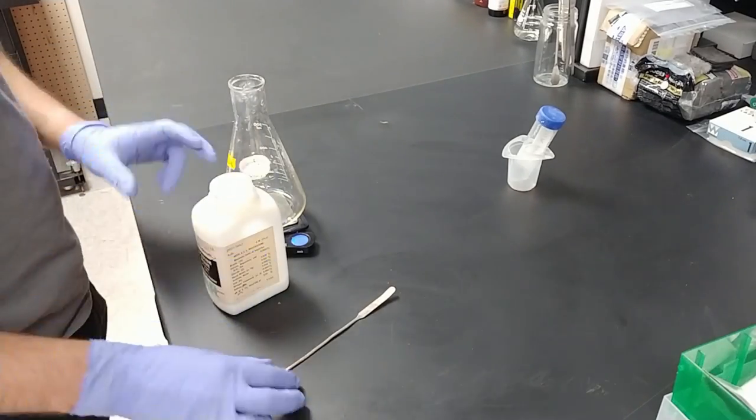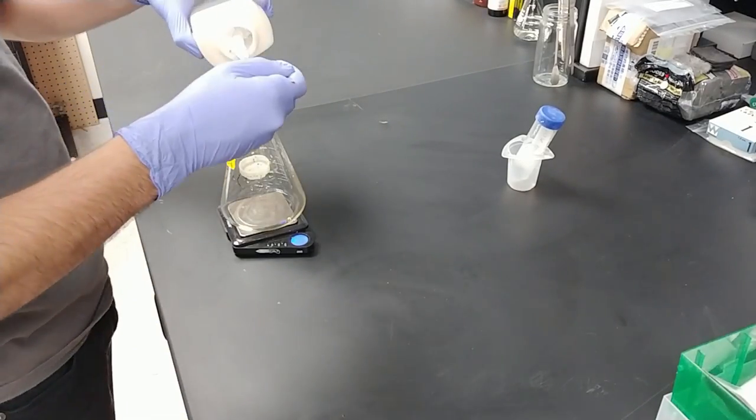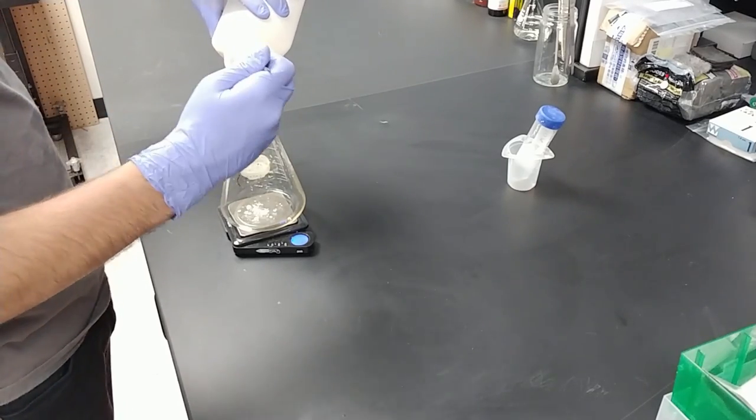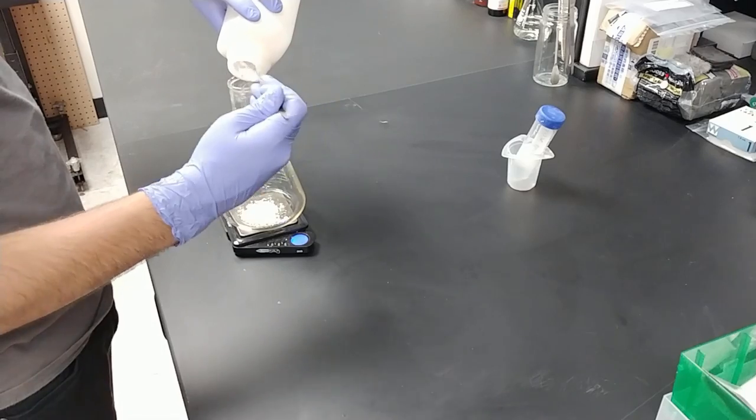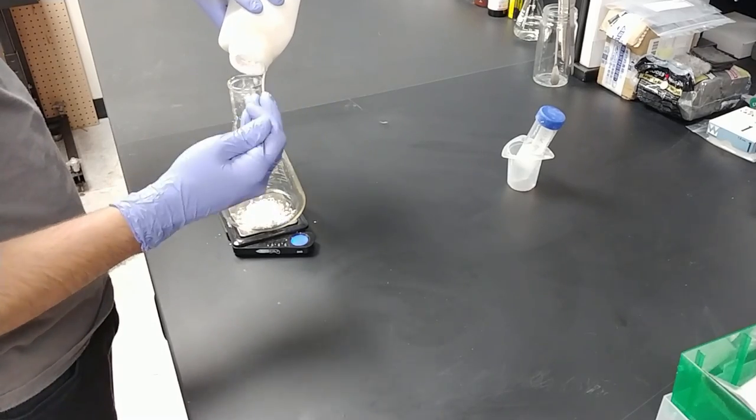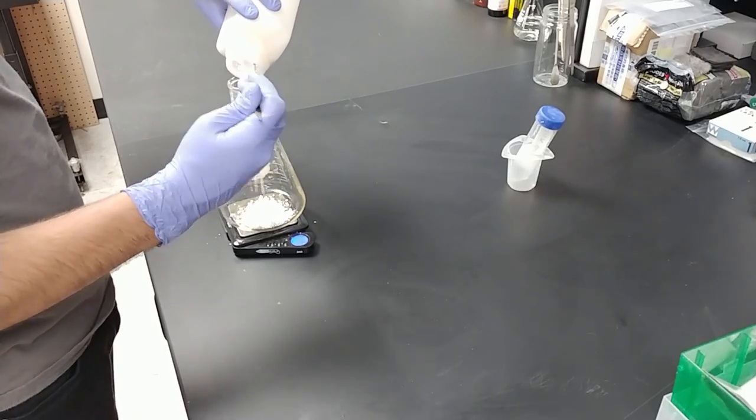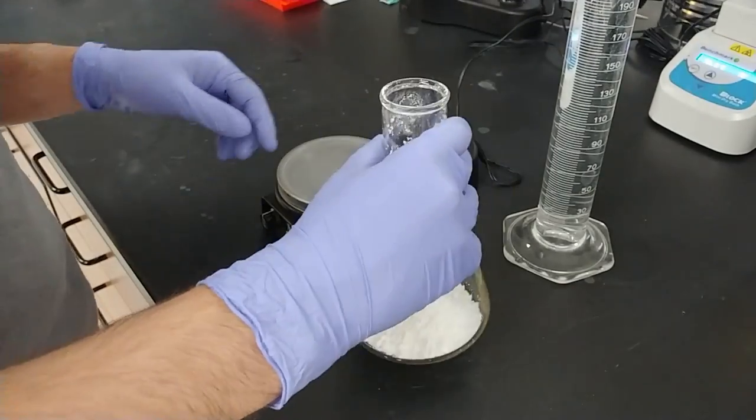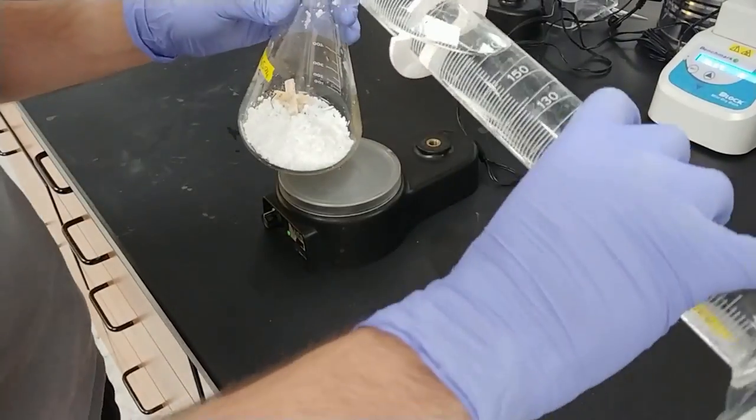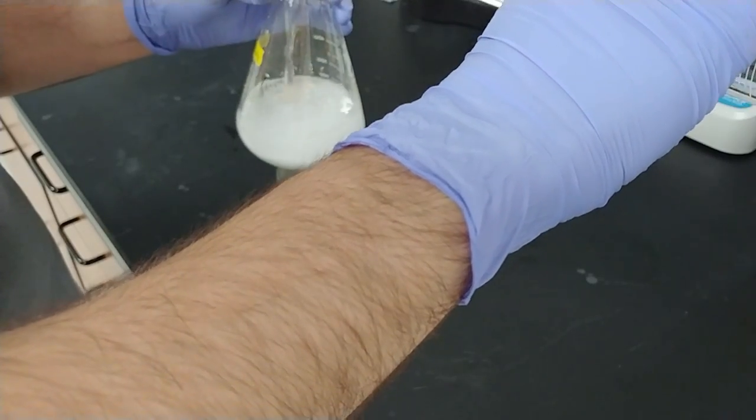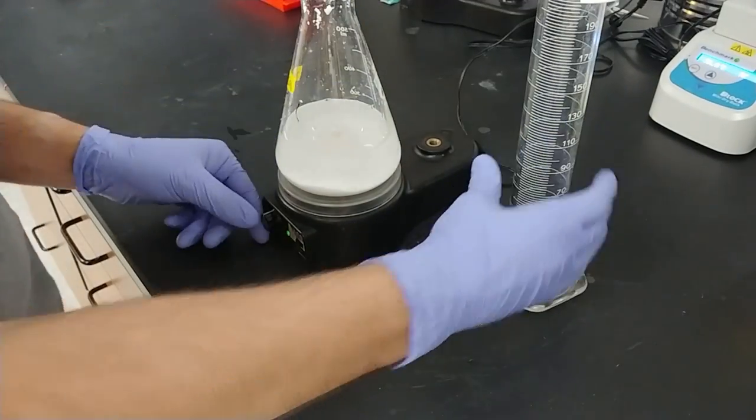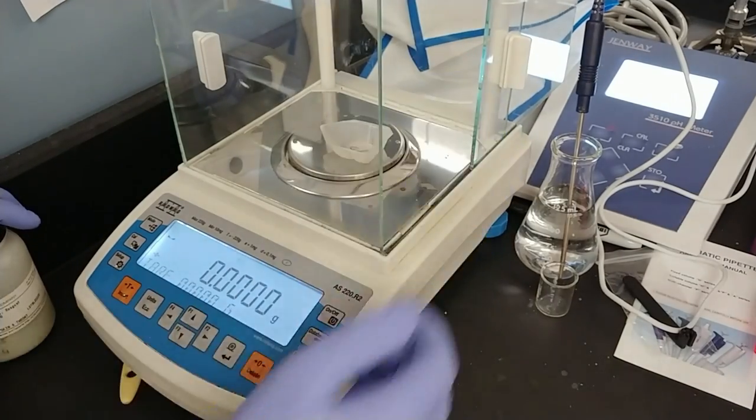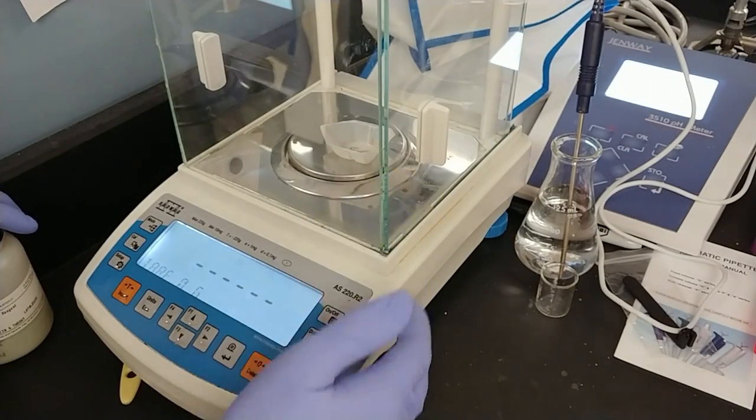The drying oven is set to a modest temperature and it's allowed to dry for a day or two. With the membrane drying we're going to make a one molar solution of potassium sulfate. So you're going to weigh out the appropriate mass of potassium sulfate and then hydrate that using a heated stir plate. Once the appropriate mass is weighed out, add a stir bar, add the appropriate volume of water. We're not being quantitative here, we're just getting close. Stir that and warm it until we have a solution of potassium sulfate.